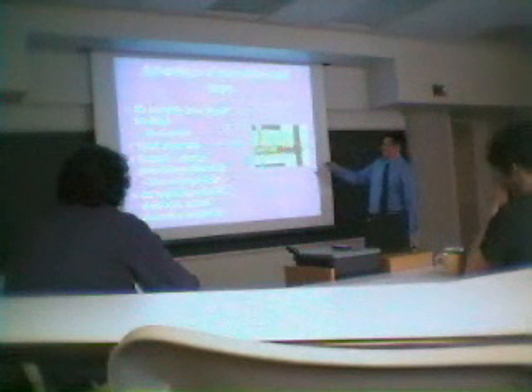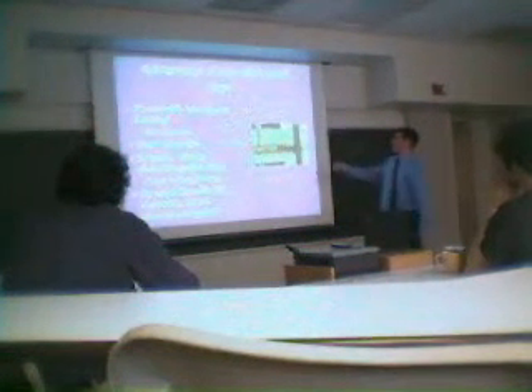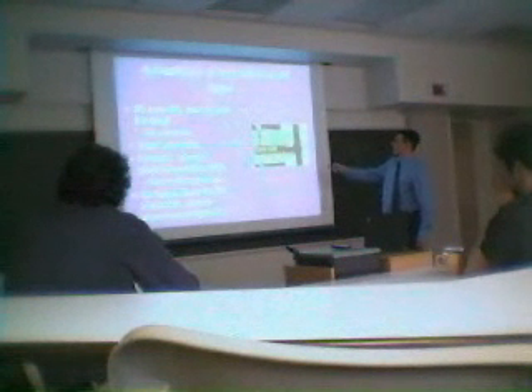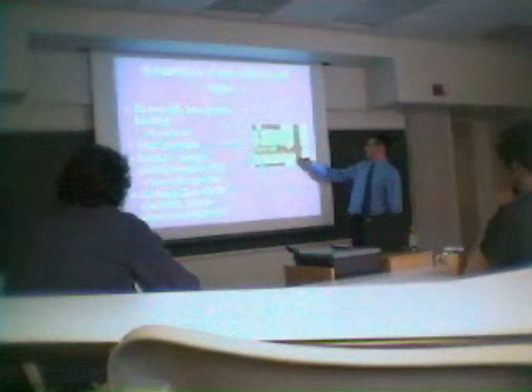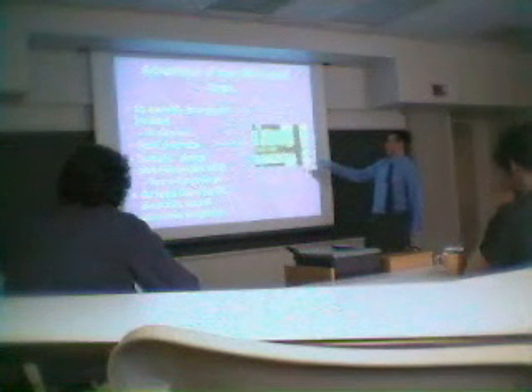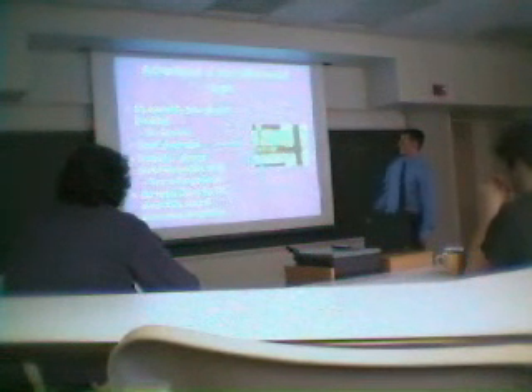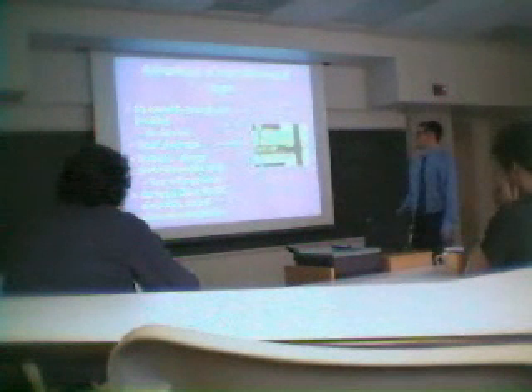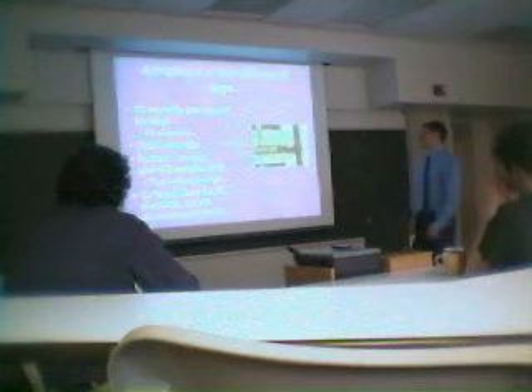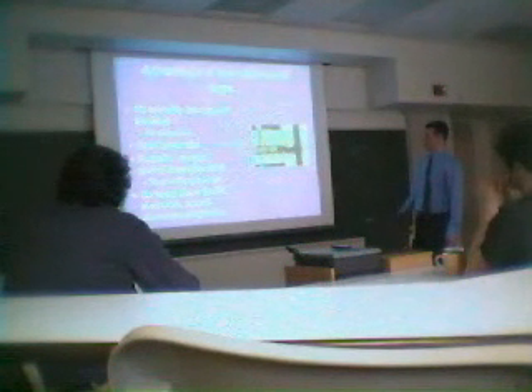Secondly, you can make really small electrodes. This picture might be hard to see, but I zoomed in on the T-trap and then put a scaled figure of the gallium arsenide trap. And you can see that one electrode on the gallium arsenide is about 1/8 of the length of, or 1/7 of the length of, the whole electrode in the T-trap. And that, in fact, is probably, that gallium arsenide trap can be much smaller as far as its electrode width.